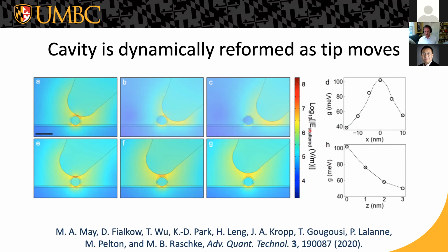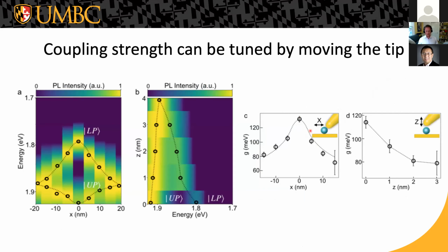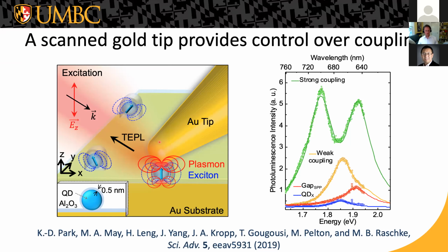It is important. The tip angle is not something that's controlled dynamically in the experiment. So the tip is fixed at about a 30-degree angle, I think, 37-degree angle to the surface. And the reason for that actually is because that gives you better excitation of this vertically polarized gap-plasmon mode. So, typically people tend to have the tip oriented perpendicular to the surface. And in that case, you're coupling to plasmons that can propagate along the length of the tip. But when you tilt the tip relative to the surface, then you're coupling to plasmons that are confined vertically along the dimensions of the tip.